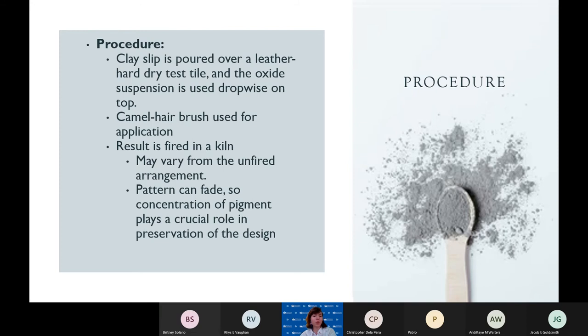Even though mocha diffusion requires two slips, here I would go into a little bit more detail as to how this process is performed. Typically, a leather-hard dry test tile is used, and the clay slip is poured over it to cover a good amount, if not all, of the surface. It is important to use a leather-hard dry test tile, because in other dryness levels, there can be a big chance that the tile can crack or chip. Then, an oxide suspension is created, and a camel hair brush is used to apply the oxide dropwise upon the ceramic surface. The interfacial tension and the instability that exists between the two liquids then develops a design. The resulting tile is usually fired in the kiln, however the temperatures of the kiln can significantly change the results.